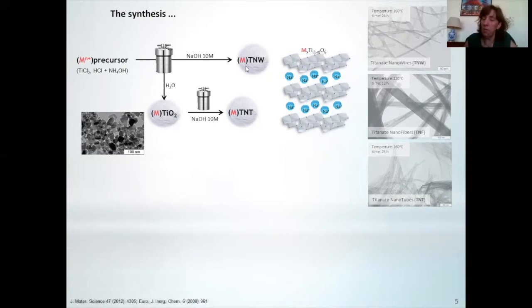In this case, when we have a doped precursor, it's not so easy to control the morphology of these particles. We are studying this process, but I can tell you, for instance, that it's almost impossible to prepare doped nanofibers because we always have smaller particles. We are studying this point.